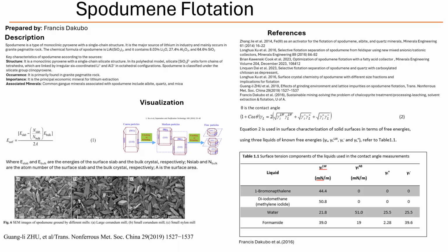Okay, so chemistry is key, but let's circle back to particle size. You said there's a sweet spot. Definitely seems to be. The data often shows recovery peaks in a certain size range. One paper mentioned 38 to 45 micrometers as being optimal. That's tiny, like fine dust or silt. Very fine, yes. If the particles are much bigger, they might be too heavy for the bubbles to lift efficiently. If they get too fine, other problems arise.